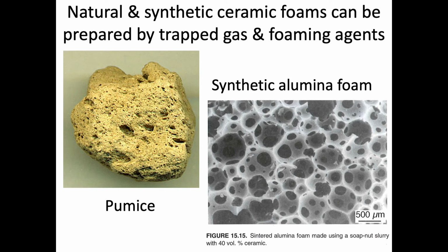And so there are natural ways to do this, and there are also synthetic ways to do this as well. Pumice is a good example of a natural ceramic that is very porous, and the reason this happens is during the formation of pumice, gases get trapped, and they can't escape, and so they create these pores. You can see that porosity very visibly within this material. We can also do that in a similar way synthetically with ceramics. We can add materials like foaming agents that would result in the same thing. When heated, they decompose and allow you to form that porous shape.